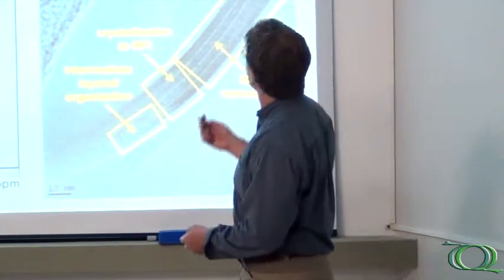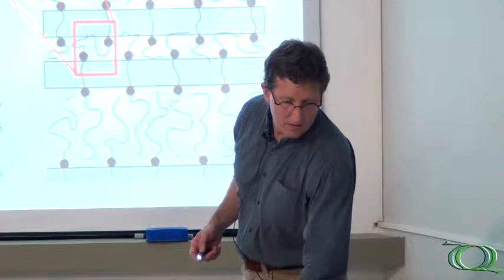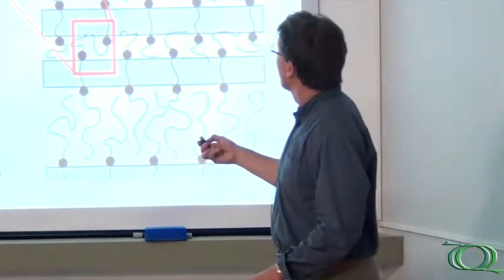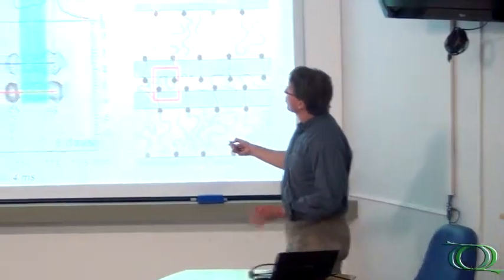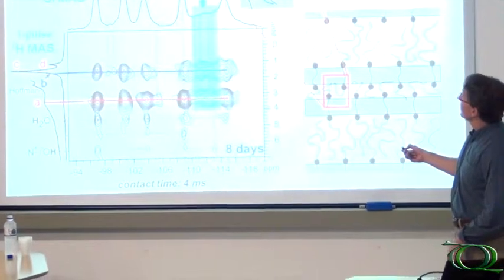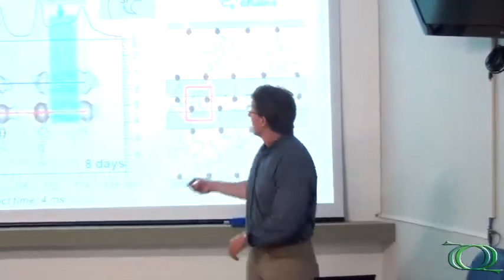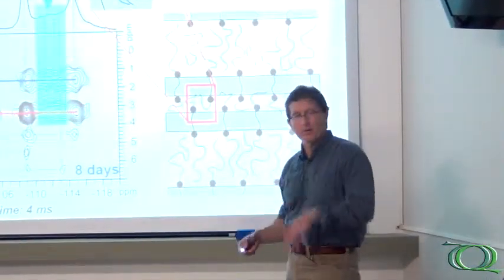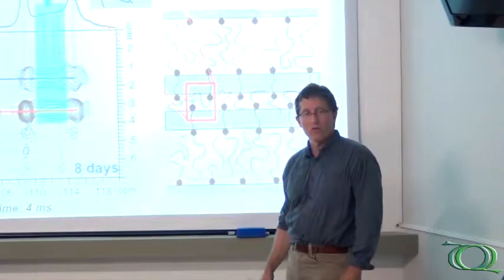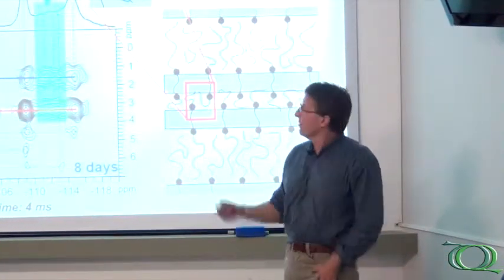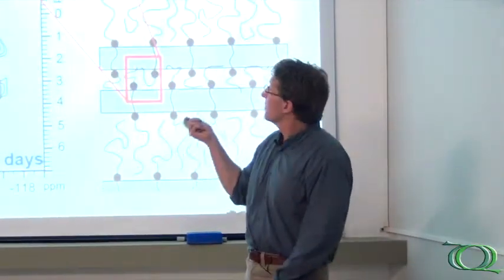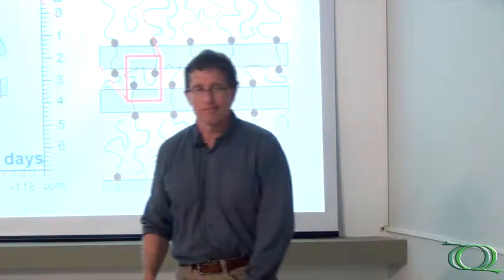These surfactants are all electrostatic. They're electrostatic in the sense that they have the quaternary ammonium, so these are charged. It's the electrostatic charges on this that cause it to interact with different silicate sites. So it's only electrostatic, no covalent bond. And with the saccharides, it's only hydrogen bonding. We can make an ormosil, an organically modified silicate, and do something similar. But in this case, we have only physical interactions.